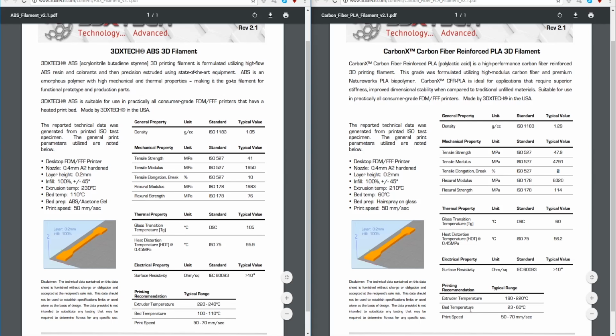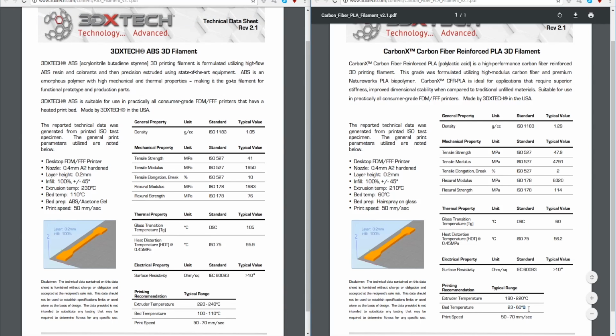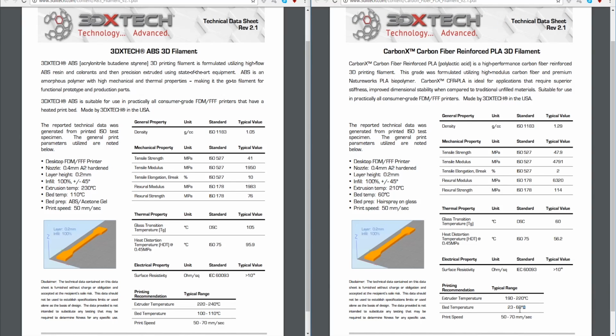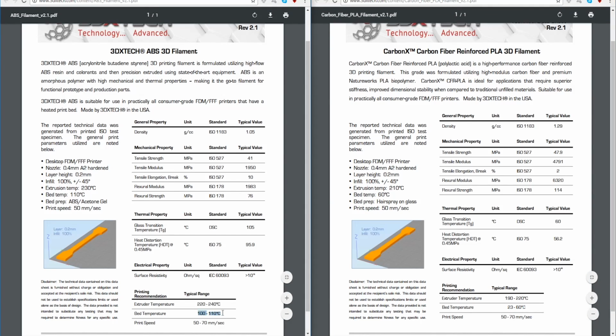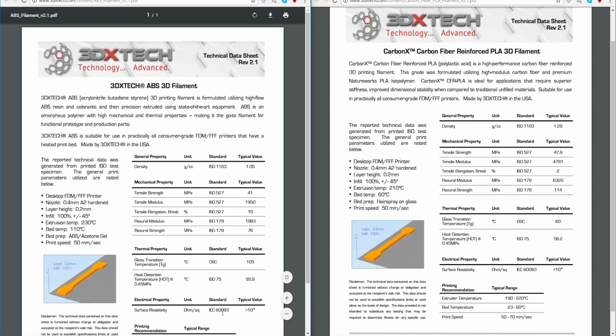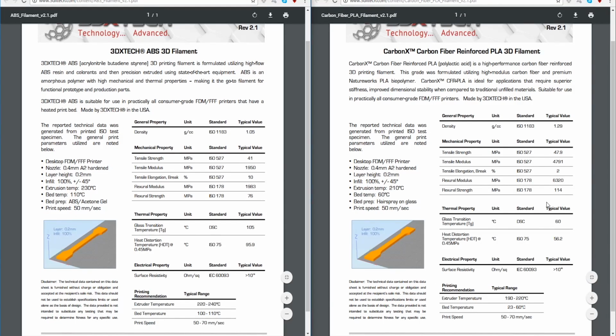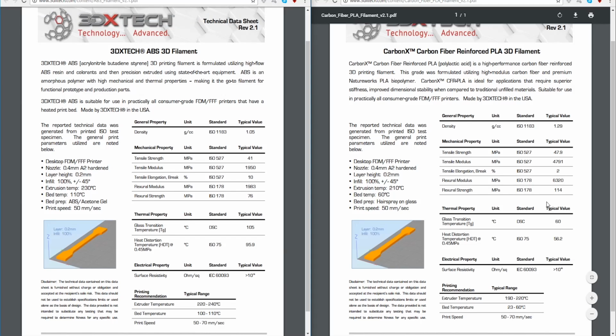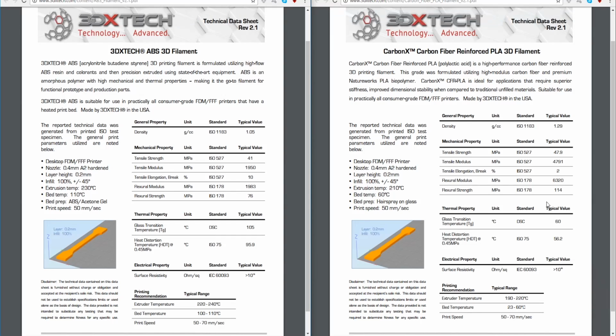But obviously you see here, bed temperature, you could print with 23 Celsius, so 24 Celsius is like 76 degrees Fahrenheit. And so you can see that you could have it just room temperature or 60 C, but here you want 100 to 110 C for ABS. It's quite a bit better stiffness for, you know, a lot less the heated build plate.